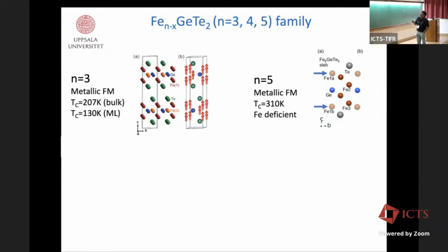If you go to N equal to 5, which is a little bit more complicated actually, you see, as usual, the tellurium atoms on the upper side and the lower side. This is just a monolayer drawn here. Then you see that this iron 1, what I call the sublattice iron 1, has a split occupation site. It is iron 1A and iron 1B. One is on the upper side, one is on the lower side. So the iron 1 sublattice has a split occupation. This has also been observed in some experiments, so that's why it has some importance here. And then the iron 2 sublattice, iron 3, and all these other iron atoms pop in, and then these germanium atoms come in between.